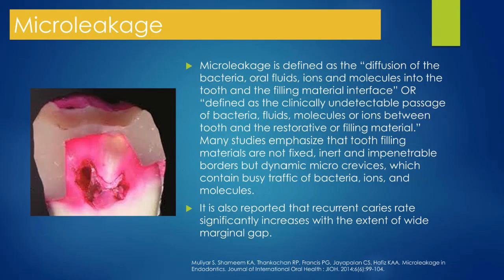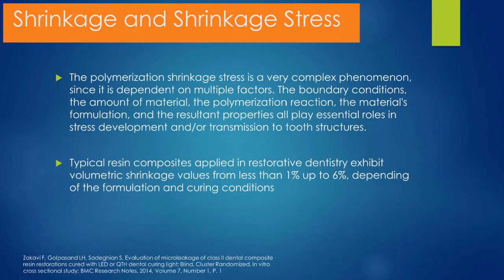We know that the wider the marginal gap is, the more likely we will have microleakage, and the higher the incidence of recurrent decay will be. We do dye penetration tests to test for microleakage, and we know that if techniques are not absolutely perfect with direct composites, then the marginal gaps are higher, and so too is the amount of microleakage.